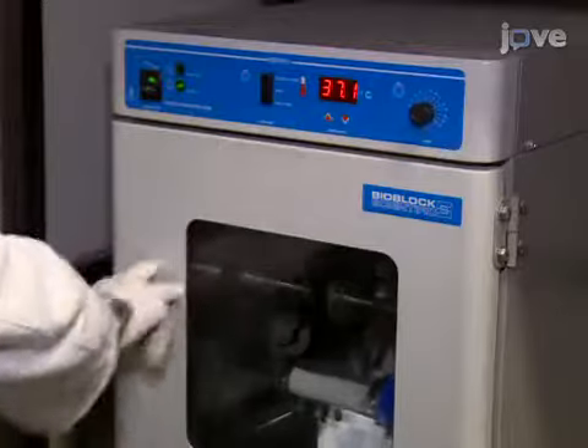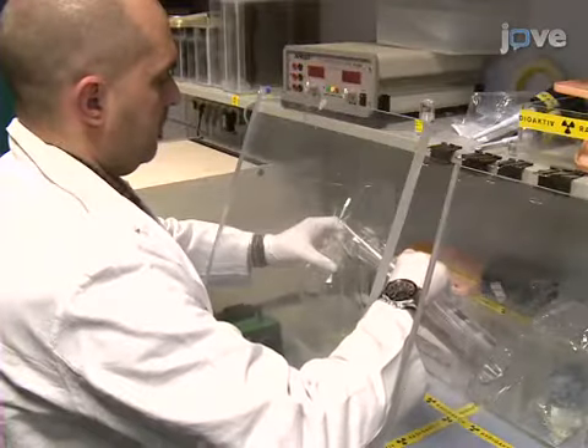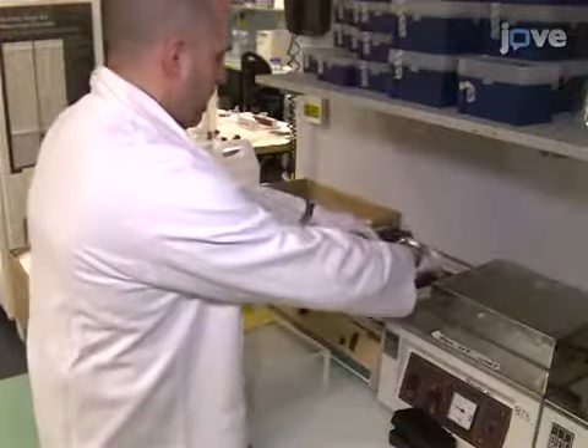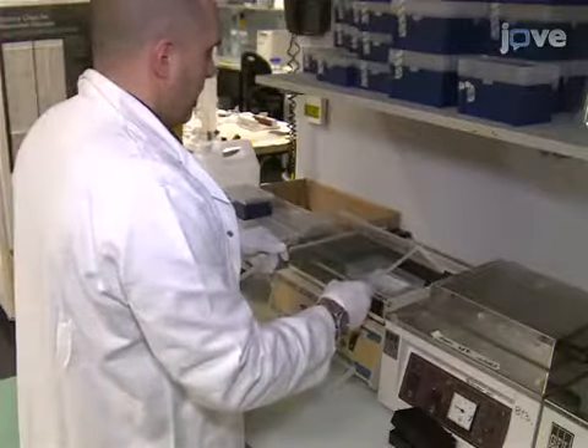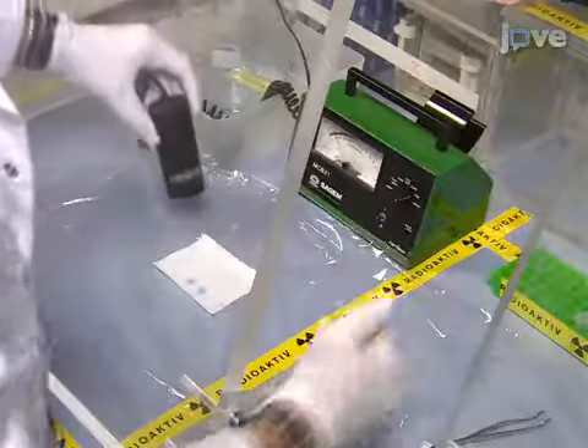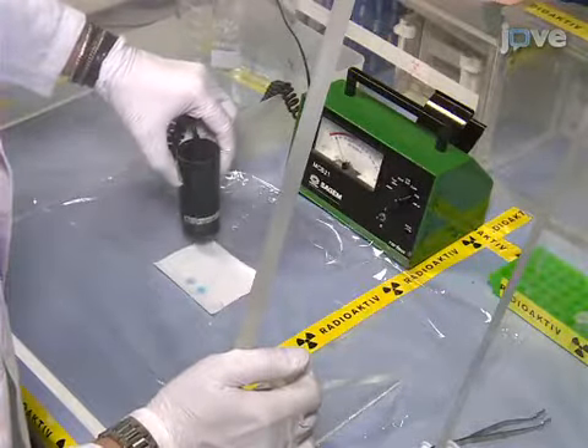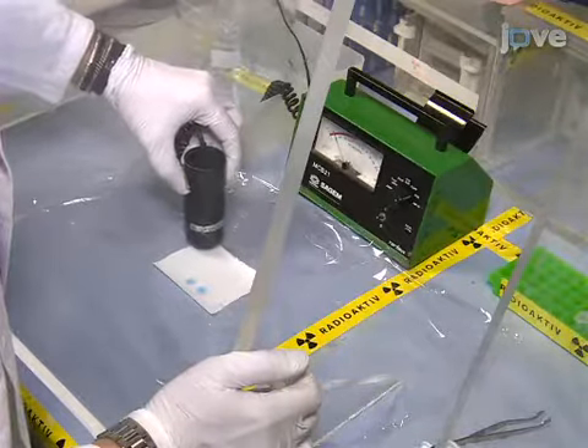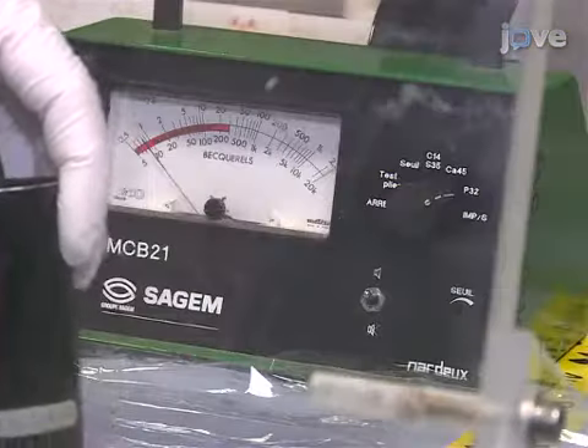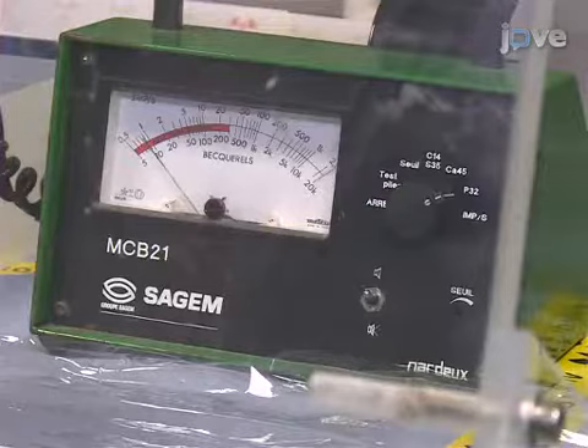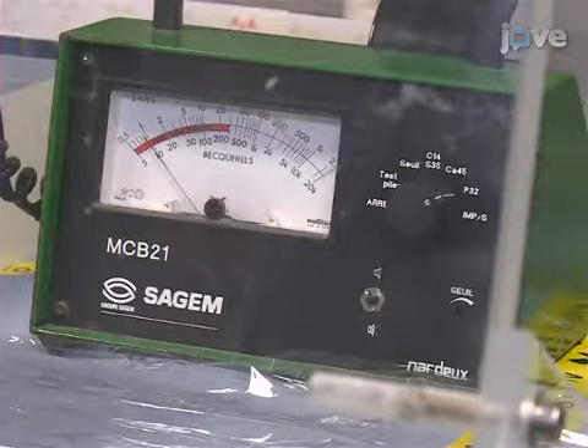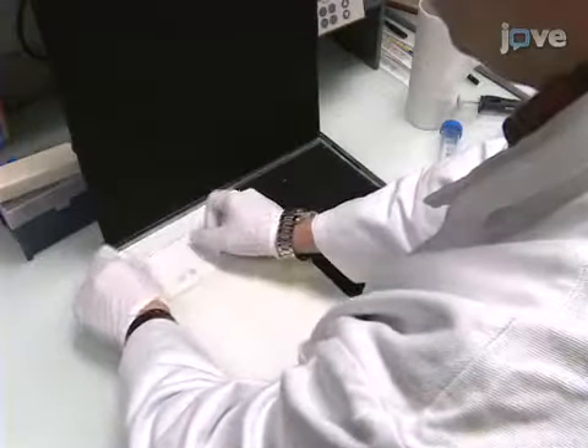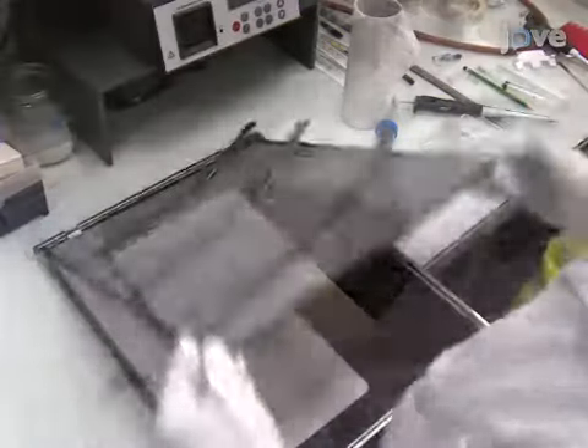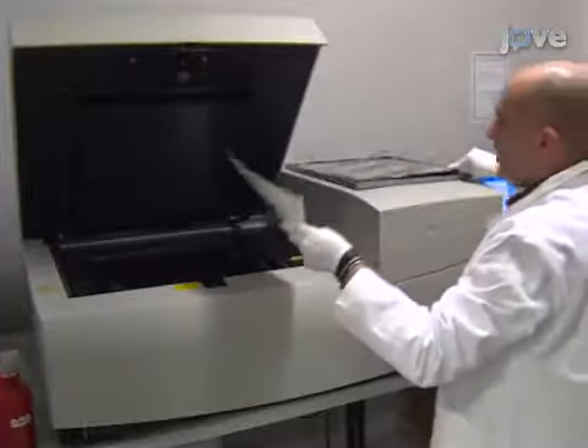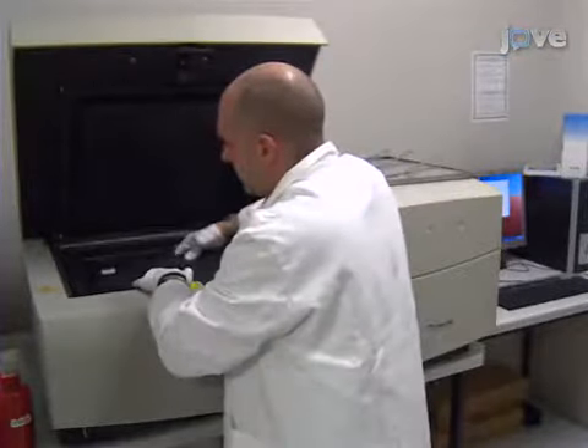Following overnight incubation, rinse the filter in washing buffer and wash it thoroughly for 10 minutes at room temperature. Then, use a Geiger-Müller detector to check for residual radioactivity at the filter corners. When the background emission is around 5 CPS, proceed to membrane exposition. Expose the filter on a molecular imager screen. Use digital conversion to reveal signals.